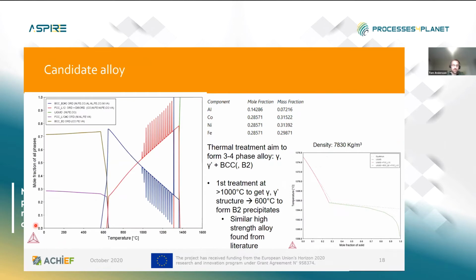So finally we came up with a few possible solutions and ended up with this kind of a 4-phase component. So this was one of those that we did minor modification for. And for this, it seems to be still usable at this 1200 degrees operational temperature, and it seems to possess this kind of a dual phase structure. And actually, we found a bit similar alloy from the literature, and at least according to that, the strength and the strain elongations were pretty good. So that's why we are quite sure that this could be a good alloy for the actual use case.